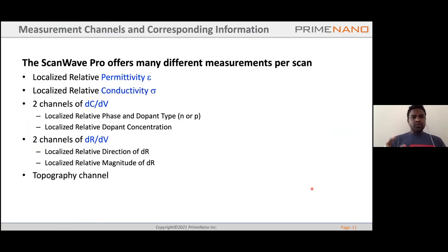So overall, in one scan, apart from the topography, you can also get localized variation in the permittivity, localized variation in conductivity. And if you look at the dC/dV signal, you can look at the relative variation in the carrier concentration and the polarity. And the same is with the resistance variation.